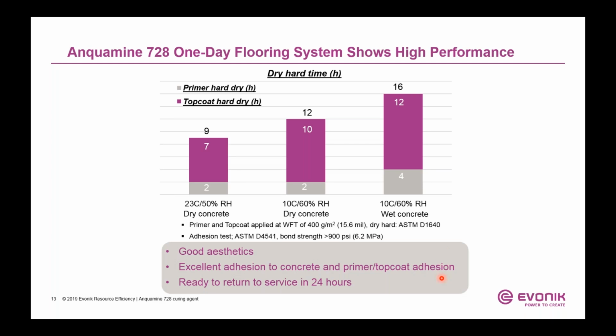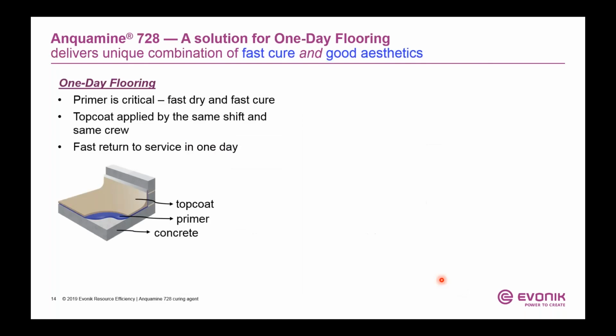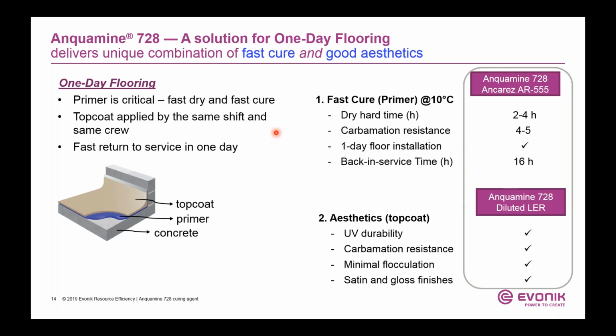So in summary, you can see that Anquamine 728 is a unique solution for a one-day floor system. It delivers a fast cure, just to refresh what I showed you before: in one day you need a primer and a top coat. The primer, the Anquamine 728 system, means fast dry, good carbamation resistance, and excellent adhesion to concrete substrate. And then the top coat shows very good aesthetics, good UV stability, minimum pigment flocculation, and carbamation resistance. So that concludes this webinar.